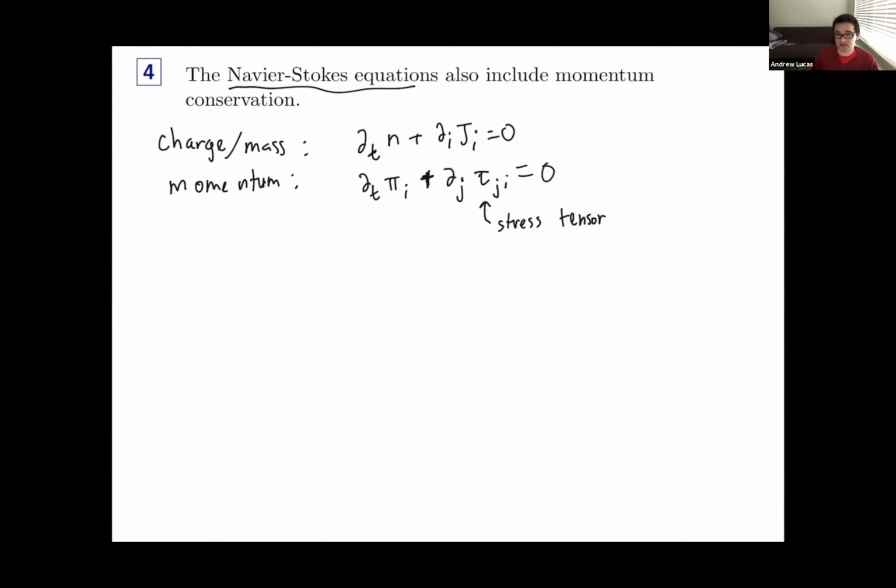Okay. And since in many metals, either due to impurities or phonon scattering, electrons do frequently scatter off of the lattice, it's often the case in ordinary metals that momentum is not conserved. But sometimes, for example in graphene, you have a metal with a very small Fermi surface relative to the Brillouin zone. So here's our Brillouin zone, and here's maybe our Fermi surface, this little small pocket here. In graphene, you'd have two, but that's not really important. We can just consider one of them. Because this Fermi surface is so small, if the electrons are scattering off of each other, they're really not going to be able to jump all the way across the Brillouin zone. They're not going to be able to Umklapp momentum away.